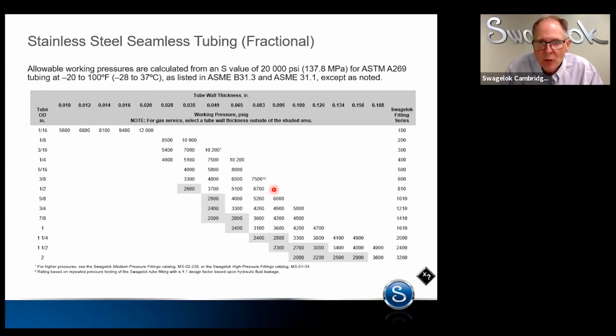If in fact you have too hard a tubing or too thick a wall thickness, you won't deform the tubing. You'll actually deform the ferrules onto the surface of the tubing and you'll end up with a frictional fit. So you think you're going to get a better pressure containment scenario going above 083 when in fact you could be getting into a situation where, if you had extremely high pressure, you could experience a blowout. So you want to stay within the recommended pressure ranges. These are the working pressures. So you can use half-inch Swagelok tube fittings up to 6,700 pounds.